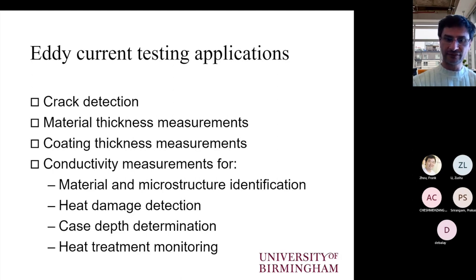Of course, we can also take into account conductivity measurements for material and microstructure identification. But apart from conductivity, we can also take into account permeability variations, which is what we use when we want to monitor phase transformation in steels. We can use eddy-current testing for heat damage detection, for case depth determination, as well as heat treatment monitoring, based on the conductivity and the permeability variations that will arise from these techniques. Of course, in order to quantify them or semi-quantitatively assess them, we need to have calibration measurements beforehand. Otherwise, we are blind and we cannot really say exactly what is the amount of phase that has formed in a particular material or a particular grade. So we need to know already from a calibration set of measurements that we can compare against what our measurement is showing.